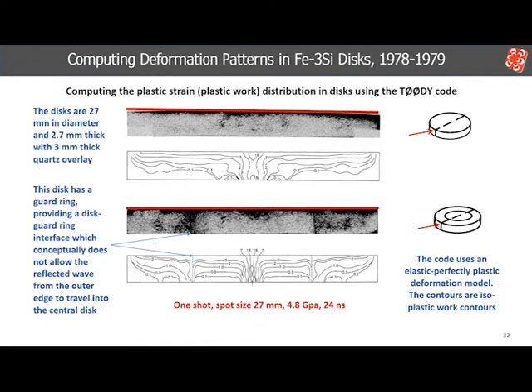In the top disc, most of the deformation is near the top surface, with 4 symmetric areas below the surface showing plastic strain. However, the computed pattern predicts intense strain along the axis of the disc, both at the top and bottom surfaces, and fading radially, which is not observed.